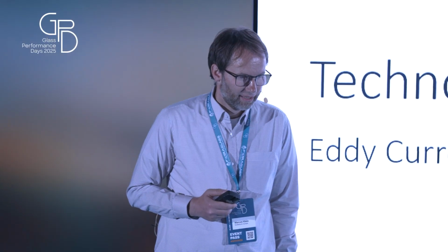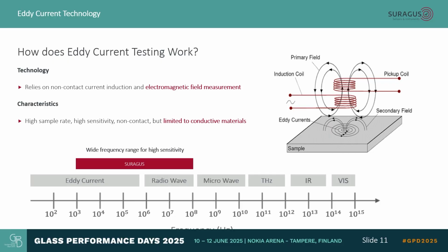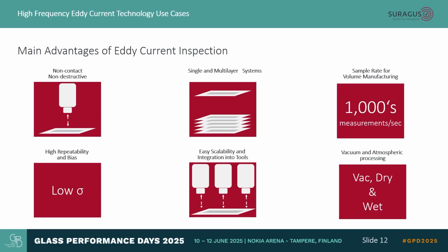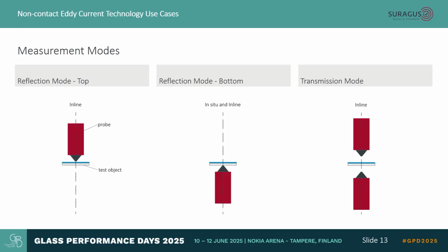The technology itself has been used industrially since the 1960s for crack testing. It's basically relying on creating electromagnetic fields which interact with conductive materials. It's a very fast technology. It's non-contact. It can penetrate through oxide layers. It can be applied in vacuum or in wet or dry environments, and it has a very high repeatability. There are different concepts: measuring from the top, measuring from the bottom, measuring in transmission mode. So that has all different pros and cons.